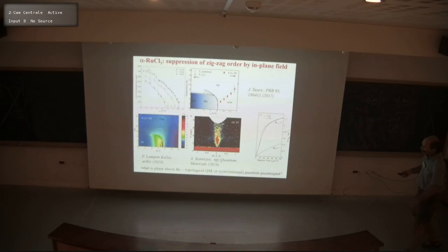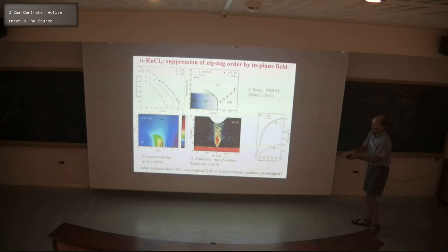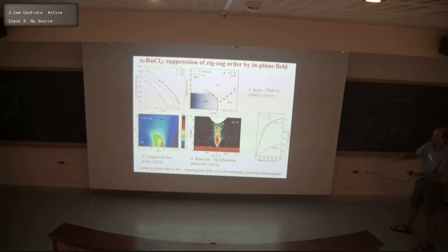So this has been refined in further diffraction measurements and also using other thermodynamic probes to show that, so here neutron diffraction, to show clearly that the zigzag magnetic Bragg peaks disappear around this kind of field. And here are AC susceptibility measurements which observe a fine detail that there's potentially another phase here that was already seen maybe in this drop here, associated with some change in the pattern between the layers, but still zigzag order in the plane.